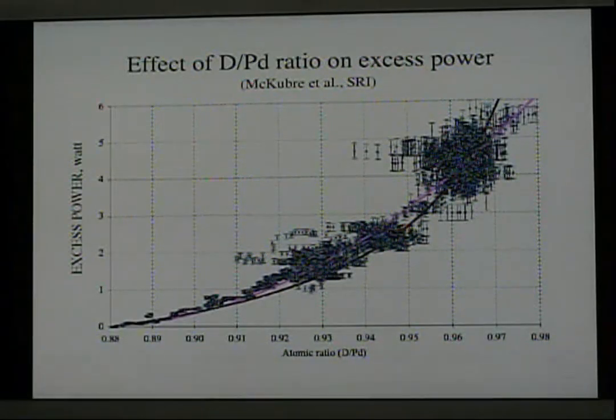Well, here's an example of the effect of the deuterium to palladium ratio provided by McKubre at SRI. You can see that when the composition, the D to Pd ratio, was relatively small, the excess energy was very small. But as the composition increased, the power increased to as much as 6 watts. Not all samples are capable of getting to as high as 0.98, and so one would never get this amount of heat. But if a sample is capable of achieving that high composition, all studies show this relationship between the D to Pd ratio and the amount of excess power.